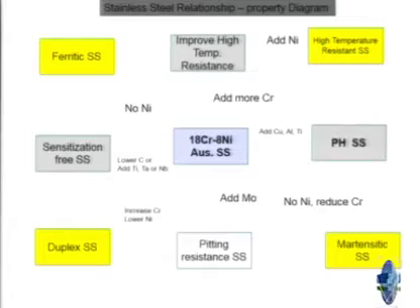And in the same way, you create martensitic stainless steel. Again, looking at the Schaeffler diagram, you have to reduce nickel to a much lower level, and also chromium, you bring it to a low level, so that at room temperature you have ferritic and at high temperature you have austenitic. That is the only way you can create martensitic, otherwise you cannot. That's why normal austenitic stainless steel cannot be martensitic stainless steel. So that is to remember. Is that all?